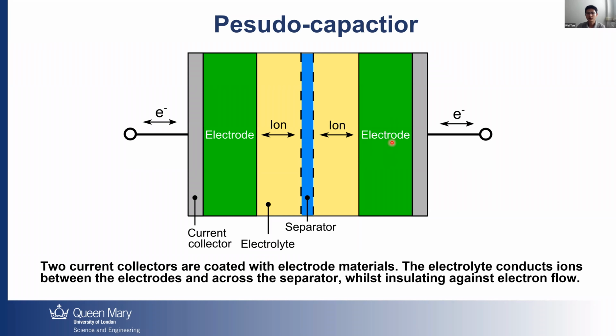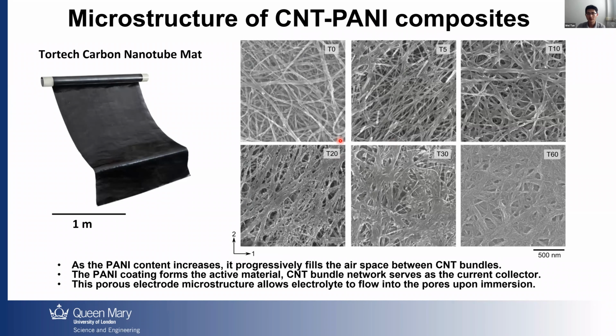In our study, we have presented a novel material called carbon nanotube polyaniline composite, PANI. Polyaniline is a material called a conductive polymer. It can allow electron transfer during charge and discharge, so it acts similar to a battery. And we have used this carbon nanotube mat as the backbone material, which is able to be coated with PANI on these nanoscale bundles.